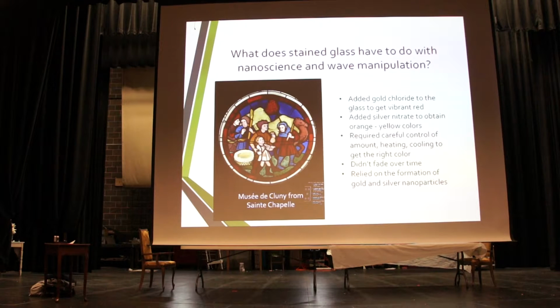The way they did it was by introducing metals into the glass. For instance, they added gold chloride to the glass, and if they added it just right, they would get this vibrant red color. And they added silver nitrate to the glass, and they could get colors from orange through yellow. It really is hard. You have to use the right temperature. You have to use the right length of time to cool it. So you know what's happening here, right? They were actually producing nanoparticles in the glass, gold and silver nanoparticles. And the interesting thing is that gold is inert, silver is pretty inert, so these are things that won't oxidize, they'll last a really long time, several hundred centuries.